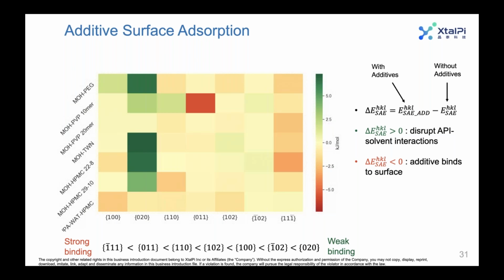I think that's intuitive. And we did see a lot of that based on the yellow, orange, and red blocks in this matrix here. But we also found that there's another mechanism whereby the polymer disrupts API solvent interactions. So in this case, solvent molecules actually bind to the surface and block the API from growing on that surface. So you can imagine how that can slow down the growth rate, therefore making that face more morphologically important. But the polymer can disrupt those interactions and allow the API to start to grow on that surface. And we saw both mechanisms. Specifically for the 020 face, we saw the latter mechanism where the polymer disrupts the API solvent interactions.